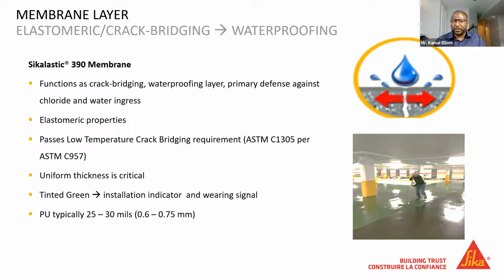We at Sika tint our 390 membrane green. It's a translucent tint, so it tells us that the membrane is going down, and if it's not applied thick enough, you can see through it. You can see the concrete through it. And also in the future, if you're several years down the road and your system is wearing and you start to see green, that's a signal indicator that you need to reestablish your wearing layer or your top coat before you compromise your membrane. So the membrane is very critical. It's important that it goes down properly and at the proper thickness and is given its best chance to function.